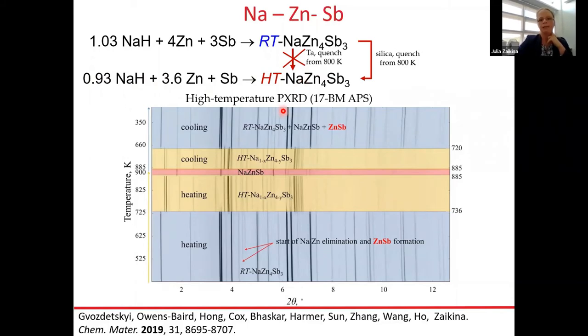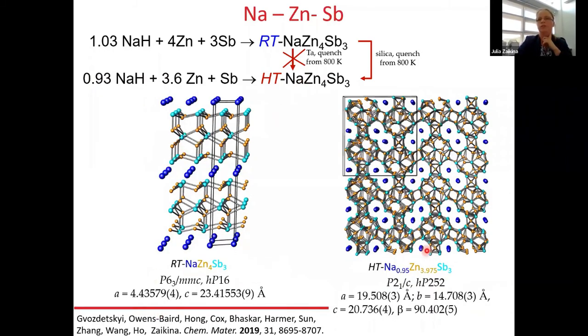So despite very similar compositions, they're not true polymorphs of each other, because this composition is similar, but still not the same as 143. So this high temperature phase is stable in a narrow temperature range, but it also needs this precise composition, particularly sodium and zinc deficit. Yeah, and then once we provide this deficit, we can also make it via our hydride route.